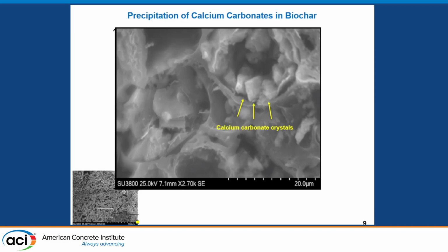But before I do that, and before we talk about this, let's talk about the mechanism. What you see in this picture is the calcium carbonate crystals that were formed inside these channels. So apparently, porous pathways that can accelerate the precipitation of carbonates, and we were able to identify all the forms of the carbonate crystals, hexagonal, cubical shaped, like I'm showing you in the picture.